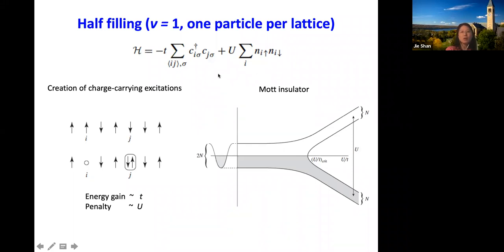But when you include the interaction, to create a charge-carrying excitation, you gain the hopping energy T, but you have to pay the penalty of U, right? So when the ratio of the two parameters reaches some critical value, it's not energetically favorable to create a charge-carrying excitation. In other words, the system stops being a metal. So this is the point of the metal to insulator transition, and the band actually splits into two, the upper and the lower Hubbard band, separated by this parameter U.